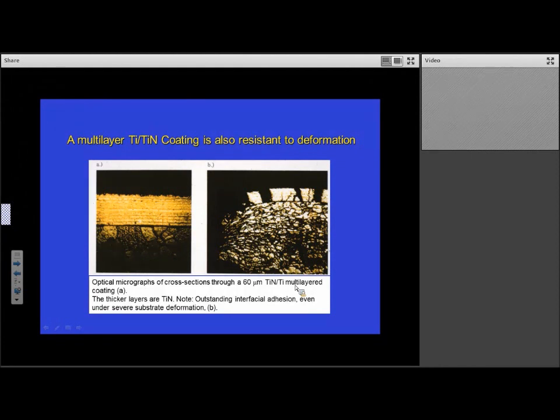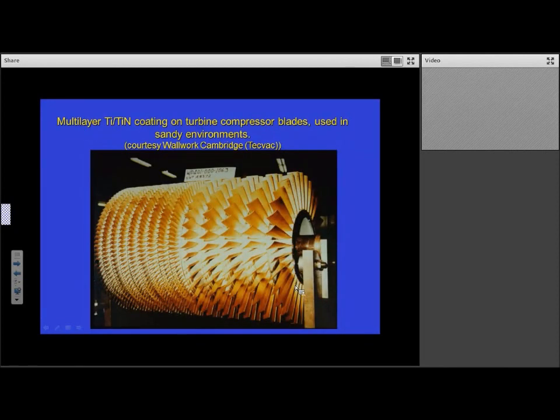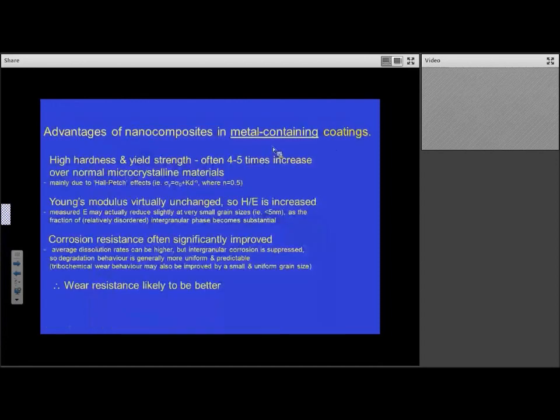There's an illustration here of a real-life multi-layer coating. This is a multi-layer titanium nitride coating. Titanium nitride coatings typically spall off at about 10 microns thick due to buildup of stress. But by having this kind of thick coating in a multi-layer, it survives and accommodates deformation very well without debonding. Those kinds of coatings are now used on compressor blades, especially where they're used in sandy, abrasive environments. This information is courtesy of Wallwork Cambridge. So a perfect example of a real-life coating which would fail if it wasn't for the fact that it combined hardness and ductility and an ability to absorb impact energy.